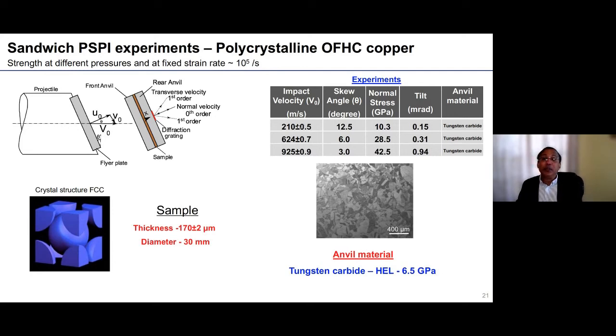So once again, we use impact velocities from about 200 to about 900 meters per second. Again, the skew angle, the obliquity angle, ranges in this case from 12 degrees to 3 degrees. The pressures range from 10 to 43 GPa, and the anvil material and the flyer material which we use are all tungsten carbide. This tungsten carbide, as I mentioned, has the Hugoniot elastic limit of 6.5 GPa. The grain size in this OFHC copper, which is fully annealed, is about 100 microns or so.